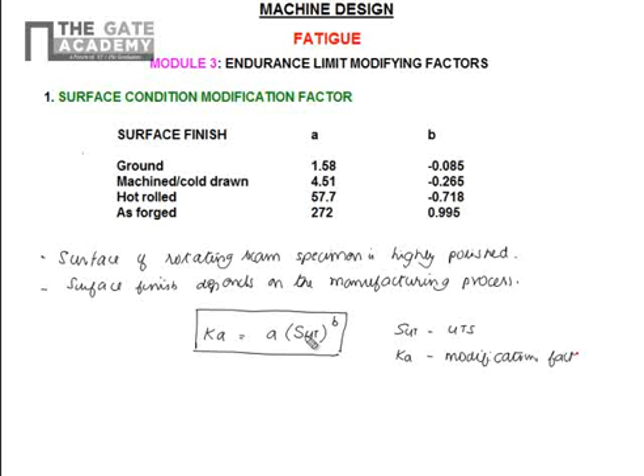A and B are the parameters which depend on the manufacturing process. If it is a ground component, the A value should be taken as 1.58, B should be minus 0.085. If it is a machined component, it is 4.51 and minus 0.265. If it is a hot rolled component, A should be taken as 57.7 and B should be minus 0.718. If it is an as forged component, A should be 272 and B should be minus 0.995. You can see the variation of A and B.